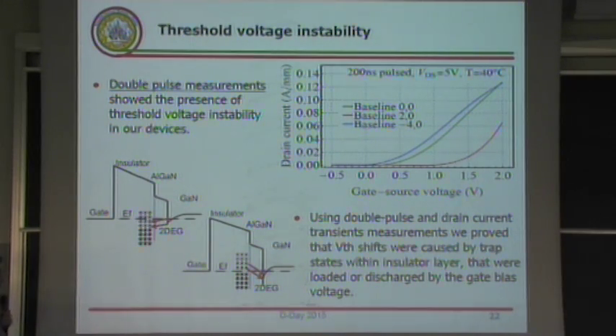And we demonstrate that these threshold voltage shifts are caused by a distribution of traps within the insulator layer. And these traps can be charged and discharged by changing the gate bias. So when we change the gate bias of the device, we are basically changing the threshold voltage. So this is an unwanted effect, obviously.